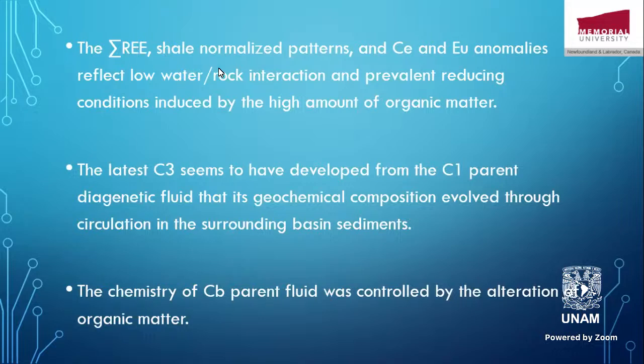The total rare earth elements, the shale-normalized patterns, and the cerium and europium anomalies reflect low water-rock interaction and prevalent reducing conditions induced by the high amount of organic matter. The latest cement, C3, the fracture filling, seems to have developed from C1 parent diagenetic fluids, and its geochemical composition evolved through circulation into the siliciclastic basin sediments, and the chemistry of the Cb parent fluid was controlled by the alteration of the organic matter.